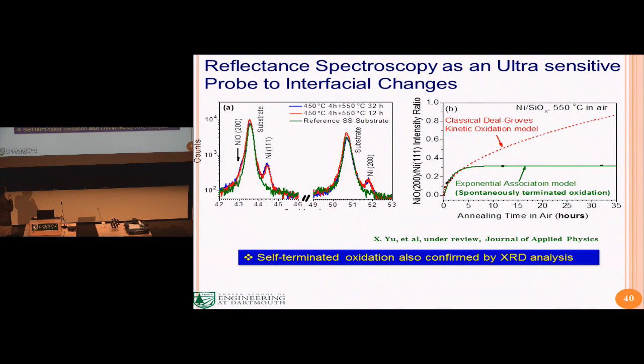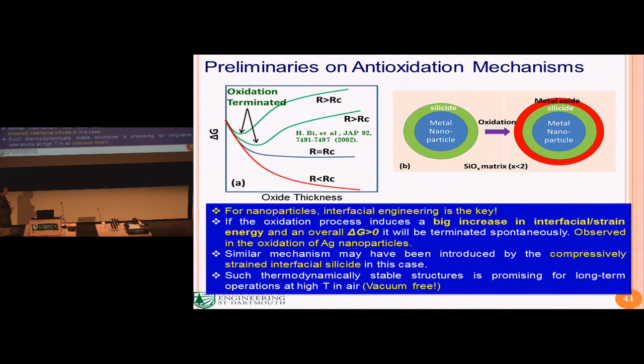We also analyzed X-ray diffraction. You can see that between 12 and 30 hours of oxidation annealing, the spectra are exactly the same. And you see this oxidation behavior compared to the kinetic model. So this is certainly a different mechanism. Our current understanding is that the interfacial energy must play a big role here. People have observed in the oxidation of silver nanoparticles that initially the Gibbs free energy will decrease. But if your particle size is large enough, eventually the increase in interfacial energy, because you introduce extra interfaces, means this Gibbs free energy will increase with the oxide thickness. So therefore, you're staying at this steady state over here. That's a thermodynamically terminated oxidation.